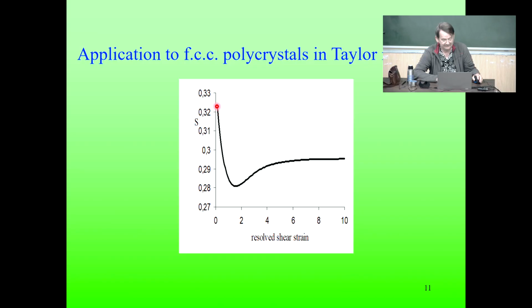If you do the whole analysis but numerically for a polycrystal, then you will get this instability parameter for a polycrystal varying, and not too much for a random polycrystal here. You see that for 0 strain, its value is about 0.33, which is basically the reciprocal value of the Taylor factor, you know. And then it is decreasing, but not too much, right? So again here for this FCC polycrystal, you can see there is a decrease up to this strain, the evolution of the orientation change is helping stabilize the deformation.